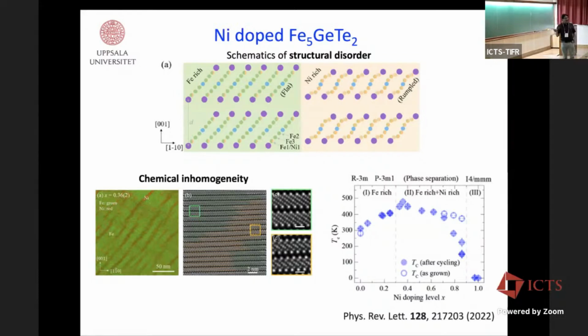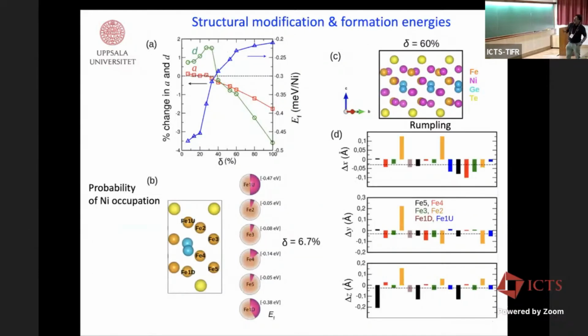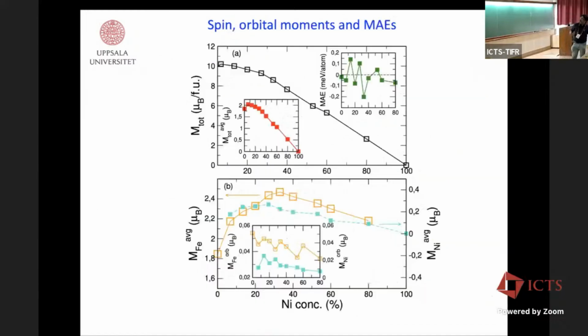Nevertheless, we wanted to have a systematic study of this as a function of nickel doping. So once again, what we found, if you look into this plot here, the probability of nickel occupation: the iron 1 up site has the highest probability of nickel occupation, and then the probability decreases here. There's a certain kind of rumpling in the structure. These are details. Magnetic moment goes down as a function of nickel concentration, a more or less similar observation in experiment. The behavior of magnetocrystalline anisotropy as a function of nickel concentration, we still do not understand. It has a very weird behavior.